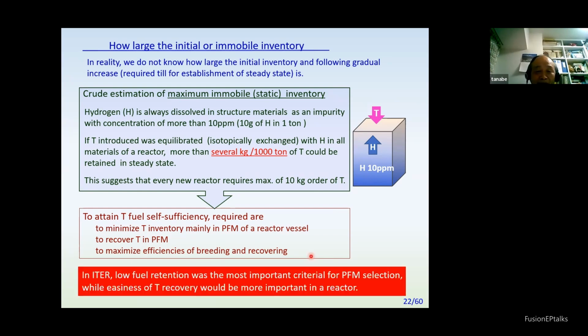In ITER's case, low fuel retention is important because they are afraid of tritium accumulation in the tokamak. The most important criteria for plasma facing material selection is low fuel retention. That is the reason for selection of carbon and tungsten as plasma facing material. However, in reactors, for easiness of tritium recovery, other reactor criteria would become more important.